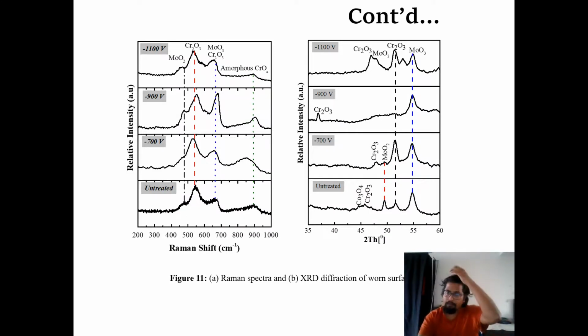And at last we performed XRD and Raman on the samples, and we found that the Raman spectra for all these samples were the same, where mostly chrome oxide and molybdenum oxide are varying based on the thickness as well as point to point. Whereas in the case of XRD, we found that in the untreated case, cobalt based oxides are the main constituent, whereas in the other cases the cobalt based oxides start disappearing, and mostly these oxides are dominated by chromium and molybdenum, which is similar to that of Raman.